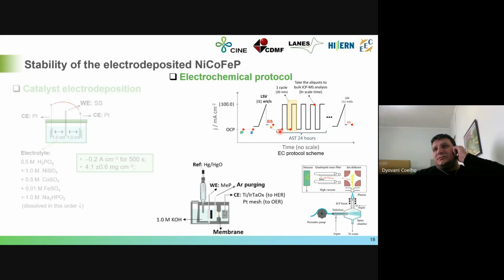So to simulate it, we have cycles keeping the catalyst in open circuit potential for 10 minutes, and then another 10 minutes applying 100 milliampere per centimeter square. So for oxygen evolution reaction, this is plus 100 milliamperes per centimeter square, and for hydrogen evolution reaction, this is minus 100 per centimeter square. The LSV is the same.